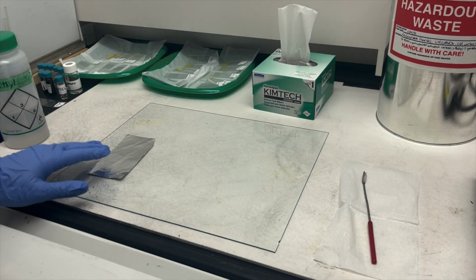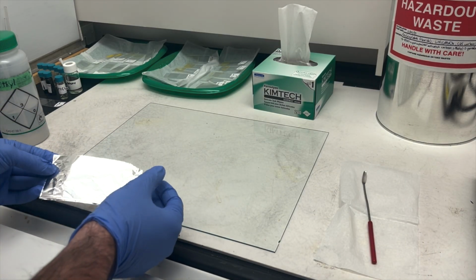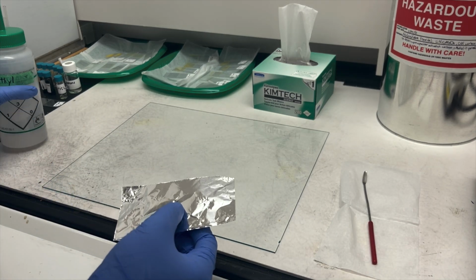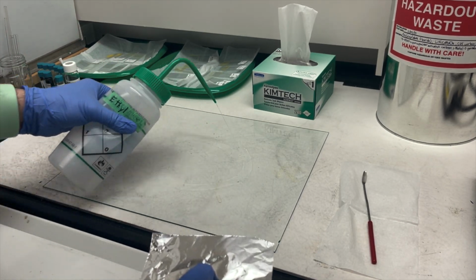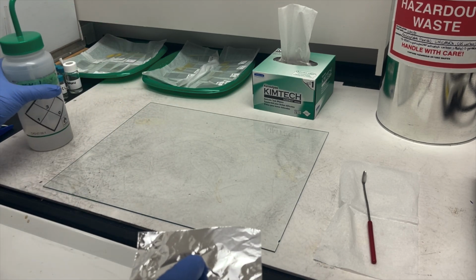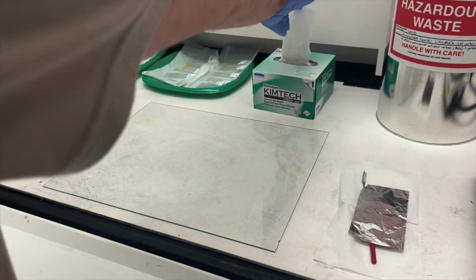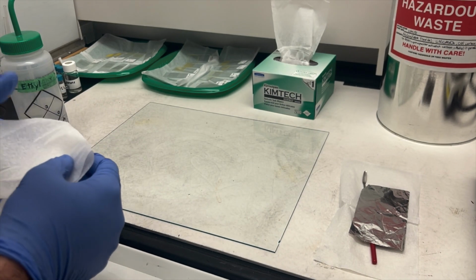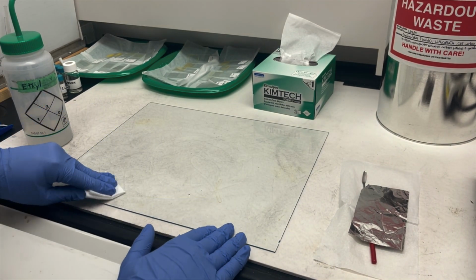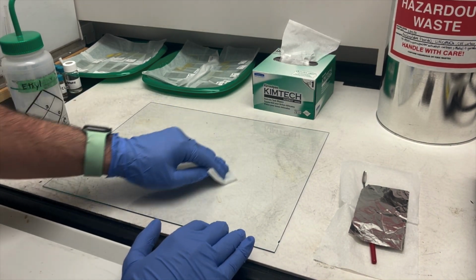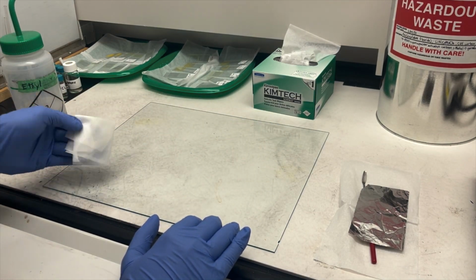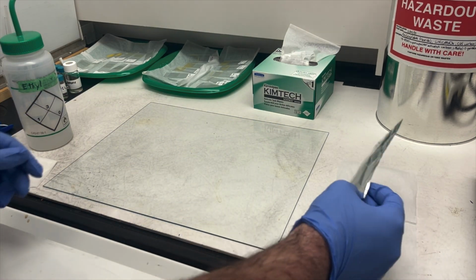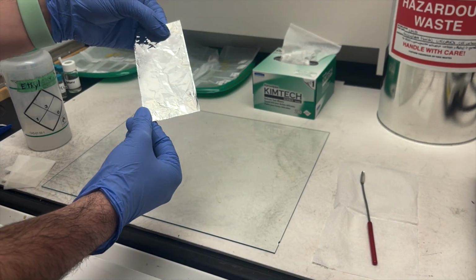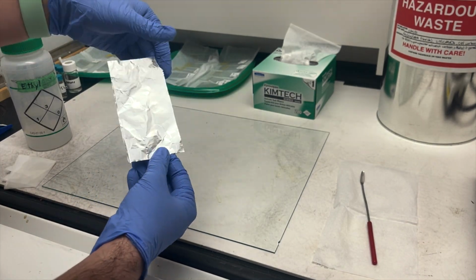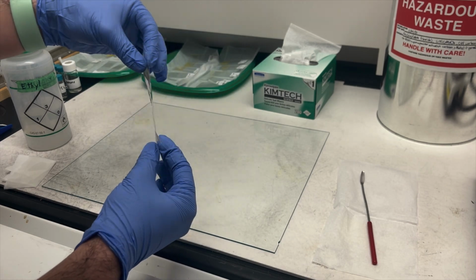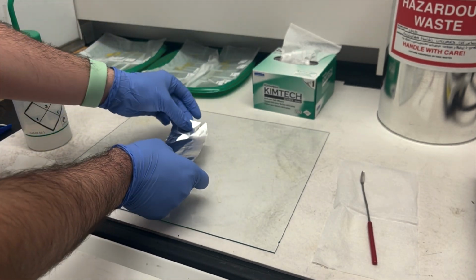In order to deposit the slurry, we will use a sheet of glass and a piece of aluminum foil cut into a strip. I will start by applying a copious amount of ethanol to the glass sheet and spreading it around with a Kim wipe. I should note then that the aluminum foil is what will be used for the cathode, whereas copper will be used for the anode. We want to cast on the dull side of the foil, so we will place the foil over the ethanol with the shiny side down.